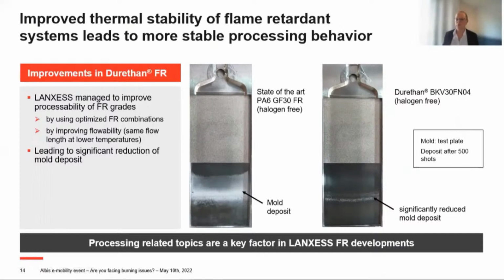And by using our newly developed, or let's say state-of-the-art material, Durethan BKV30FN04, we managed to develop a material that significantly shows less mold deposit. And this is only one area which I wanted to show you in this short time, where we managed to develop materials that show better processing behavior, even by using flame retardant materials.